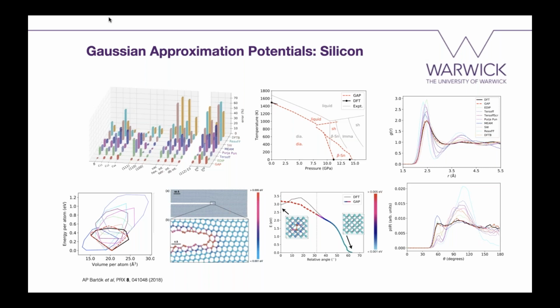As we expected, we get properties like elastic properties, surfaces, and defect energies quite well. But we also found that the potential doesn't do anything particularly bad for things that are not explicitly included, like stacking fault energies. So this is a good sign, but then the potential can do a lot more. The next figure is a phase diagram prediction for silicon, where gray lines show experiments, and black dots are DFT results explicitly. So this is what we are trying to reproduce rather than experiment, because DFT is our benchmark.